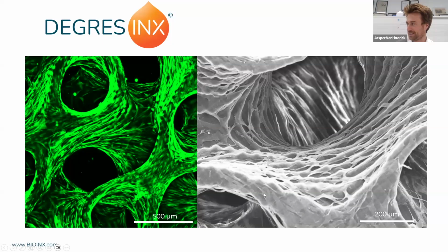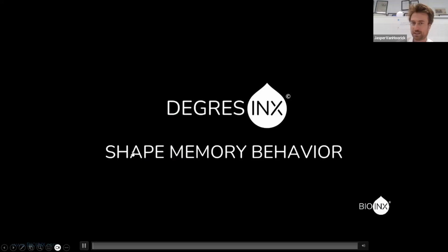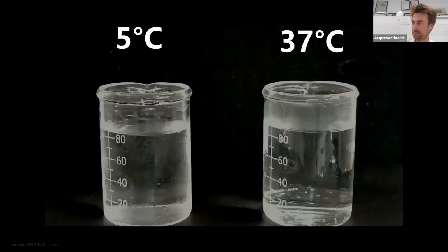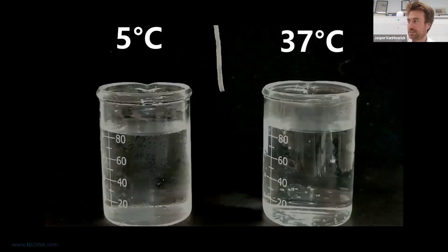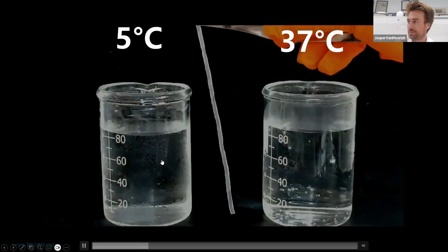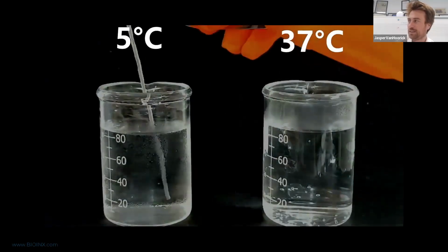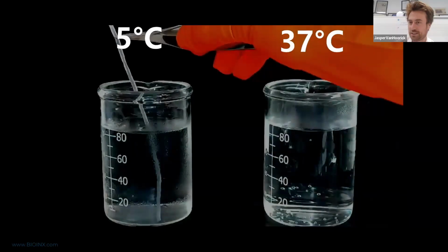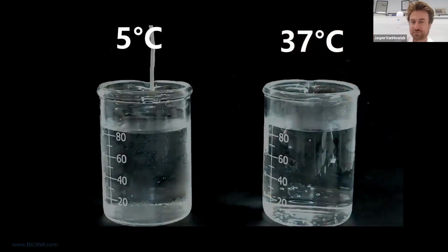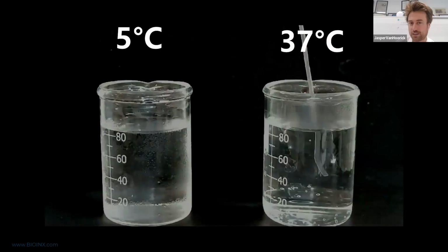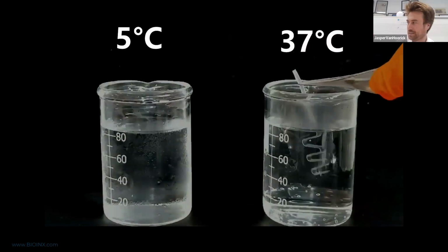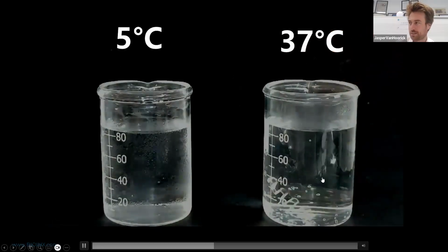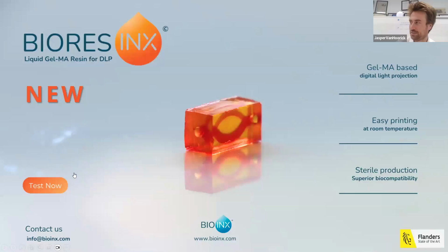The nice thing about this SEM picture is you can see the individual pixels of your digital micromirror device. Again, you can use shape memory behavior here. So you can print a complicated shape. And if you have a polymer with shape memory properties, if you heat it up, you can deform it. If you then cool it below body temperature, it stays in this temporary shape. And if you then put it at body temperature, it will go back to its complicated 3D printed shape. Something you can also use for minimally invasive applications.